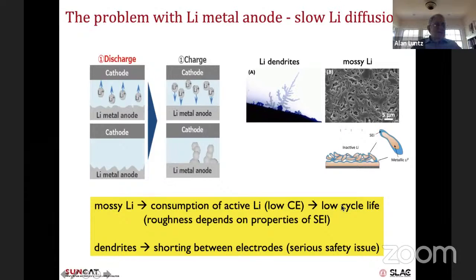Now, what turns out to be true is that tailoring the SEI by changing the electrolyte has a big effect on all these things. And we'll see an example of that in a minute. The other problem that happens is that you can get dendrites. And when dendrites grow, they actually can cause a short and a fire. So that just means you're growing at the tip of this particle. And so it's important to know when the dendrites form.